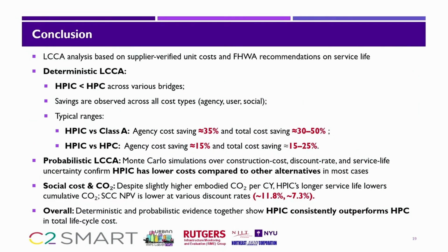So the conclusion is that for all the bridges we tested, HPIC costs are lower than the HPC costs. The agency savings are around 30 to 50% for using HPIC versus regular concrete. HPIC versus HPC, that's between 15 to 25%. Again, if you think about the number of bridges and number of projects, that might be some meaningful savings. We also did the probabilistic analysis that showed similar results, maybe lower gains due to the possibilities and combinations of different probabilistic values.